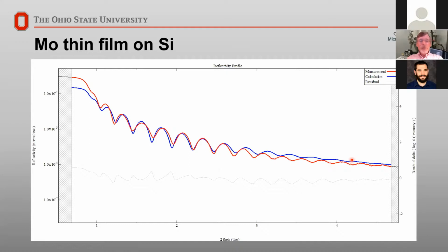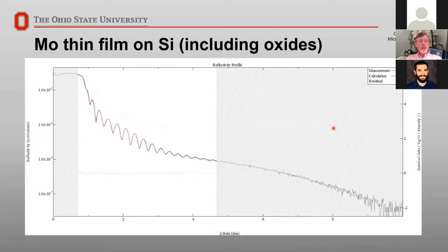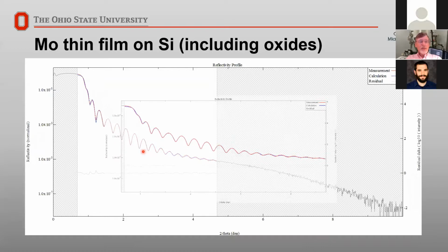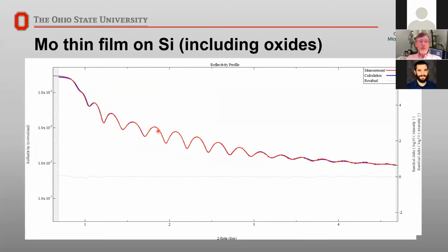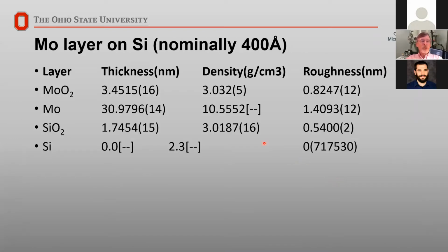When you're starting with a piece of silicon, you often have a very thin oxide on the surface. And then after they grew the molybdenum, you got a little molybdenum oxide on the surface. So once we include the oxides, now this is the way our data looks. And if we zoom in on it, you can see that our fit is much, much better. So once we include the oxides, we can come up with these numbers.